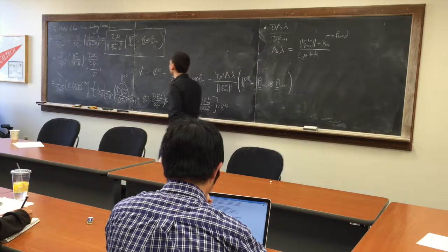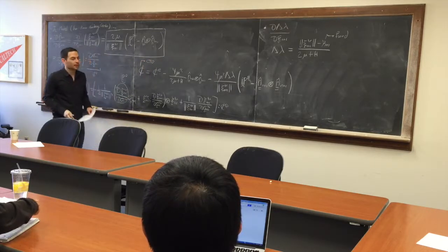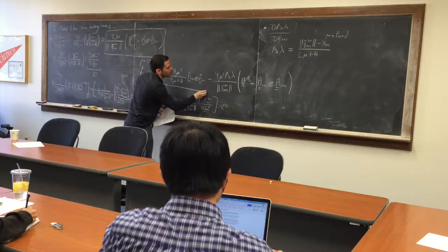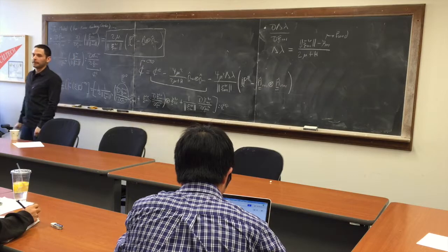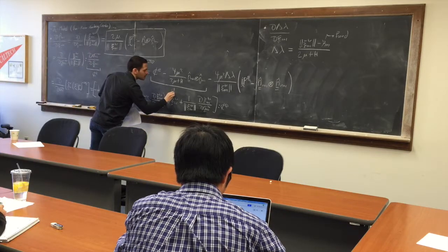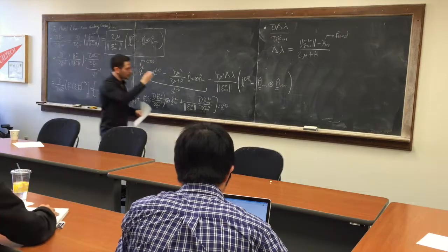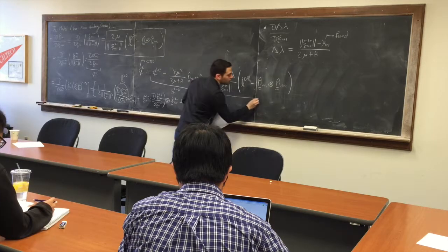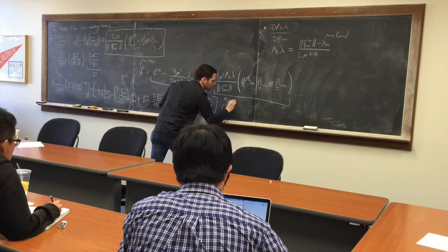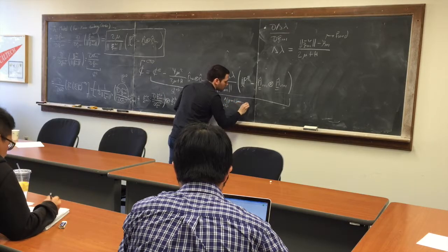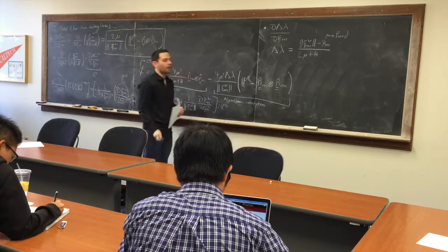All right. So this is the CTO. This is the consistent tangent operator. And if you take a look at your notes, what is this? This is CEP, the continuum, the exact one. And this part here is the algorithmic contribution, of order what?